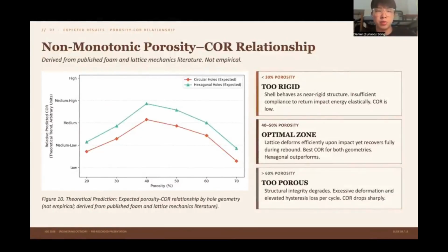Below 30% porosity, the shell is too rigid to store energy, and above 60%, it collapses. The 40 to 50% window is where compliance and structural integrity balance optimally.